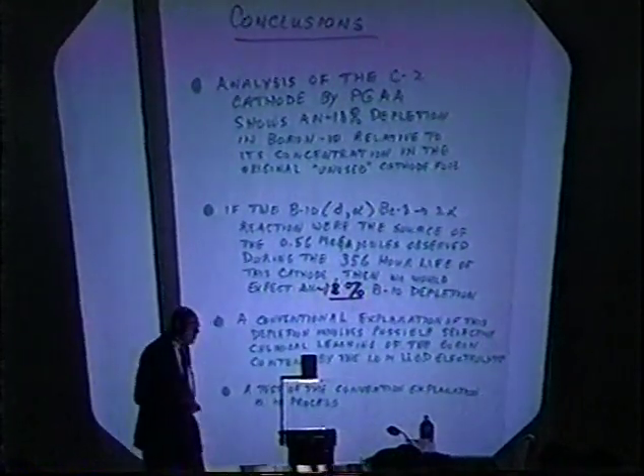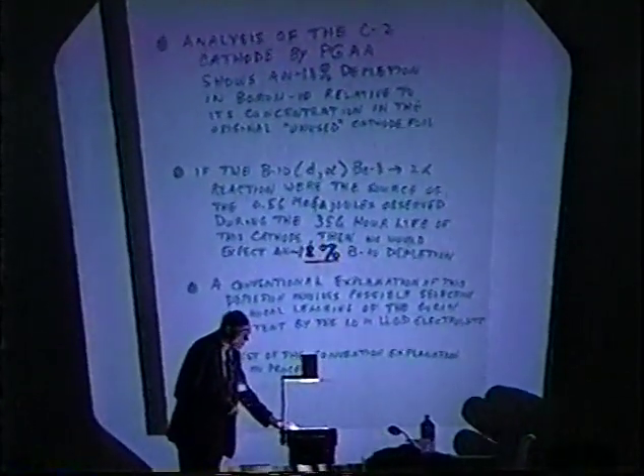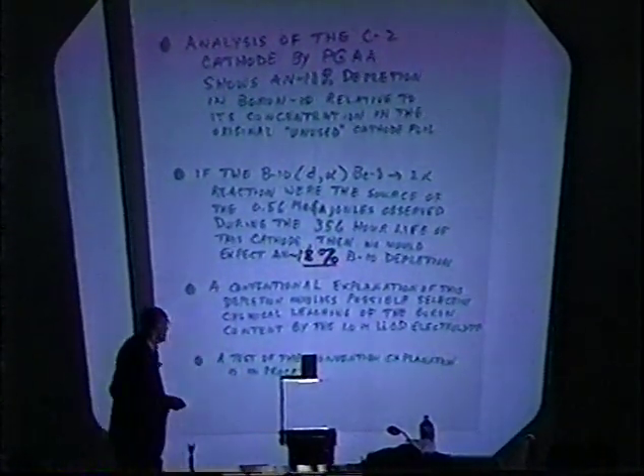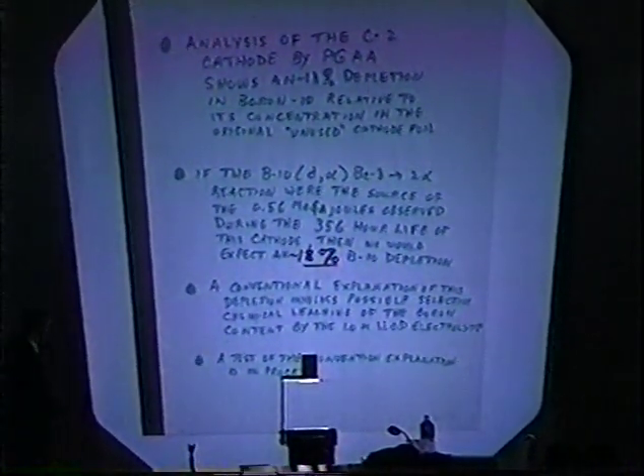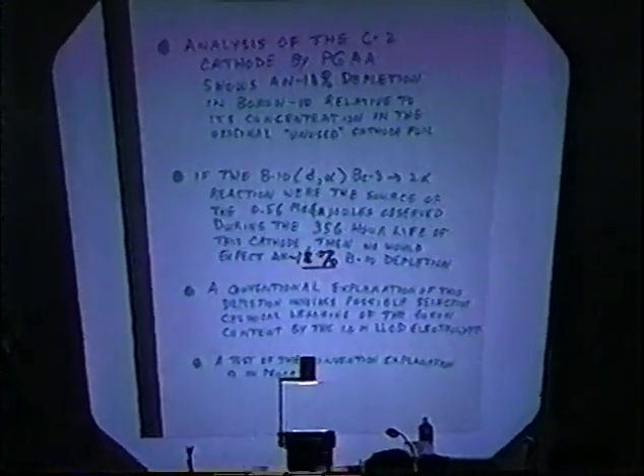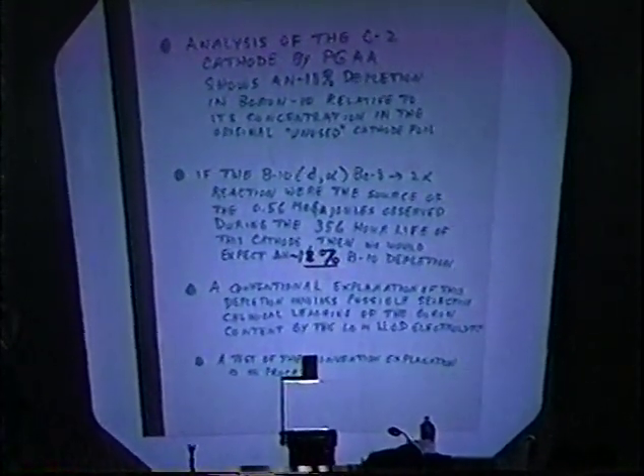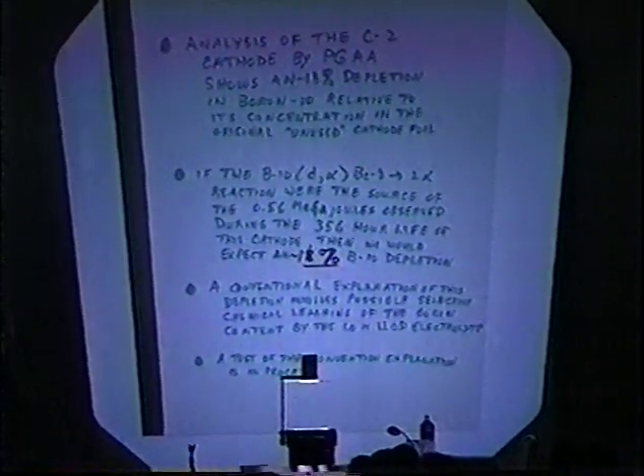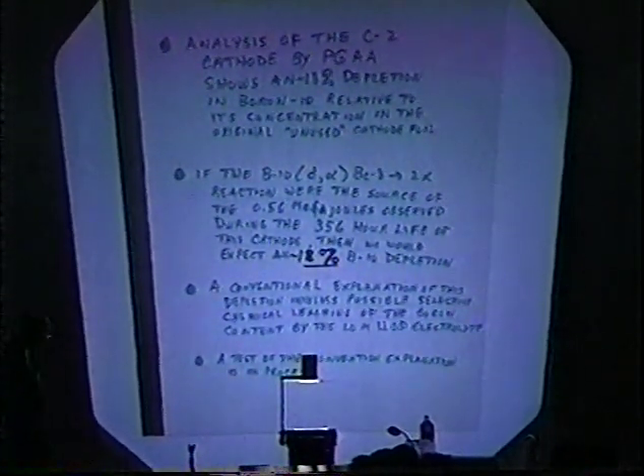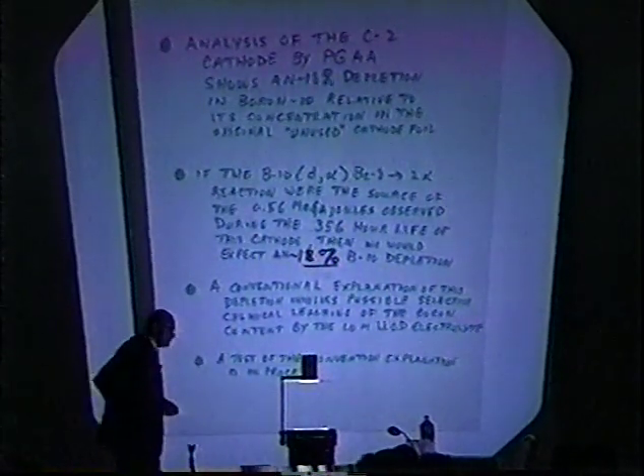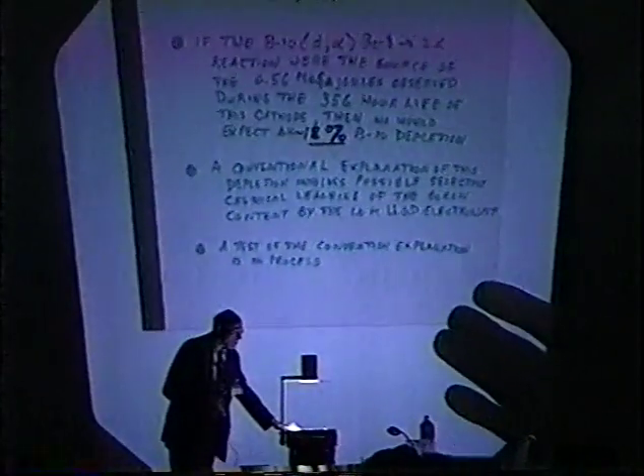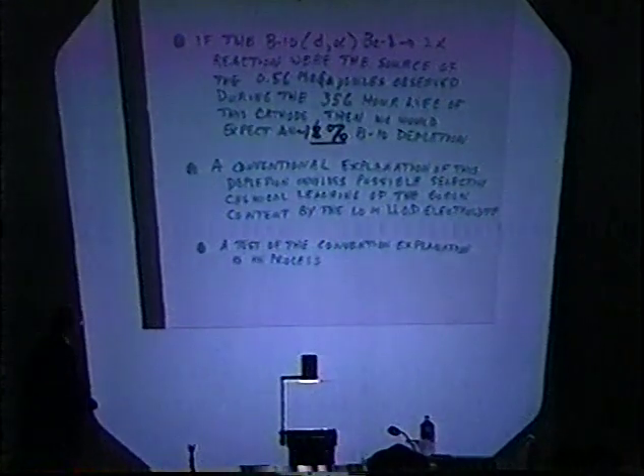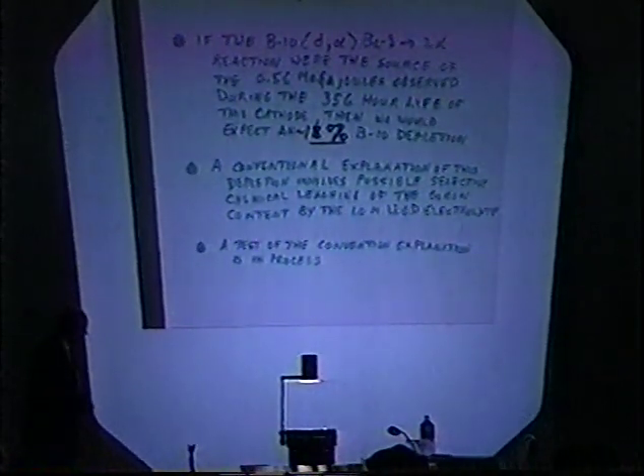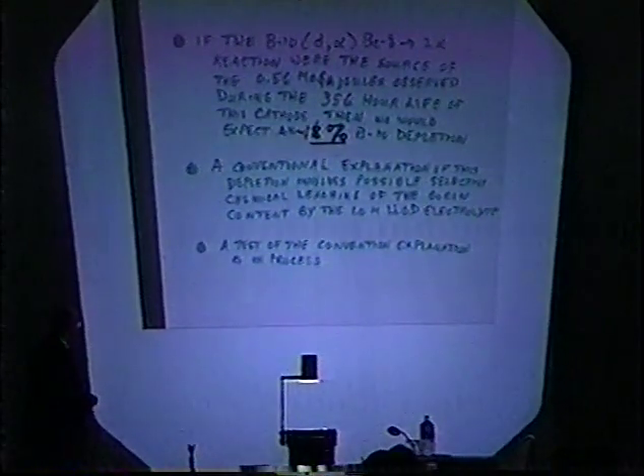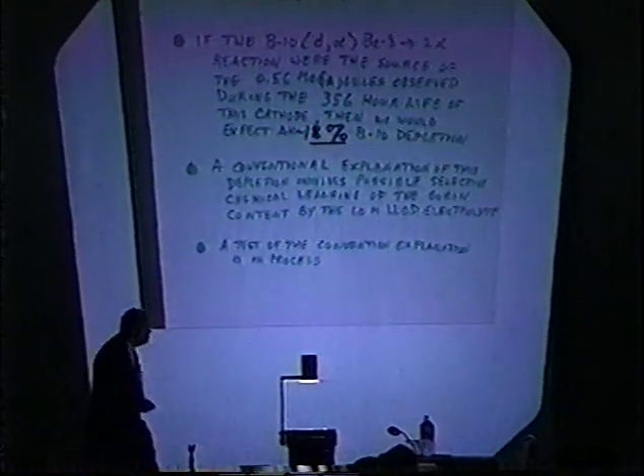I've never been that lucky in most of my experiments. So naturally we've got to be a little suspicious of it. And so a conventional explanation of this depletion involves the possible selective chemical leaching of the boron content by the 1 molar lithium deuteroxide electrolyte during that 356 hours. And I'm in the process of checking that question by running the anode, by the way, which is the same material and would be subject to dissolution of the same sort, perhaps even more, because being an anode, and that test is currently underway. Thank you.